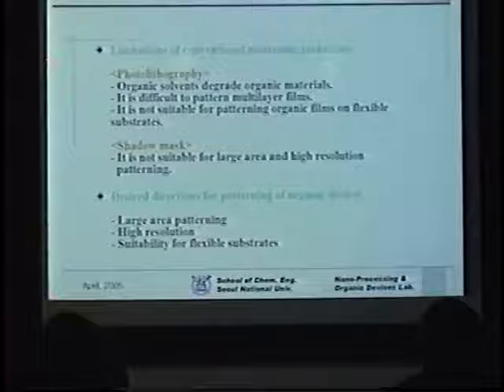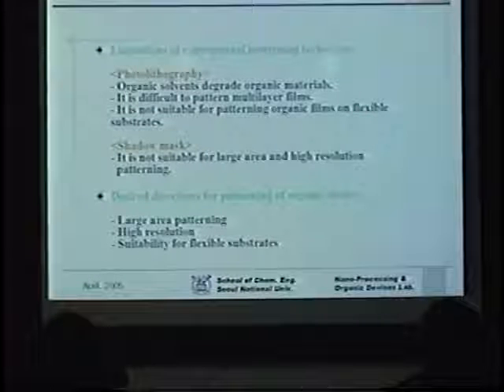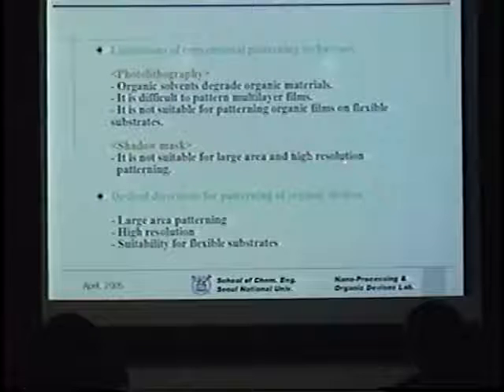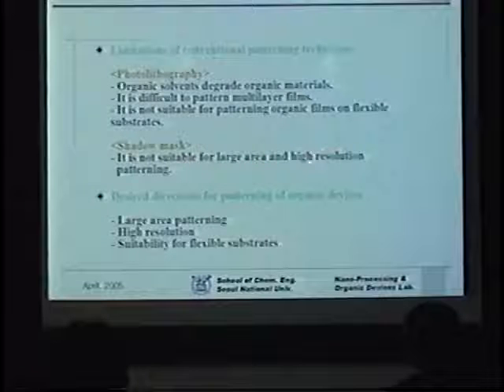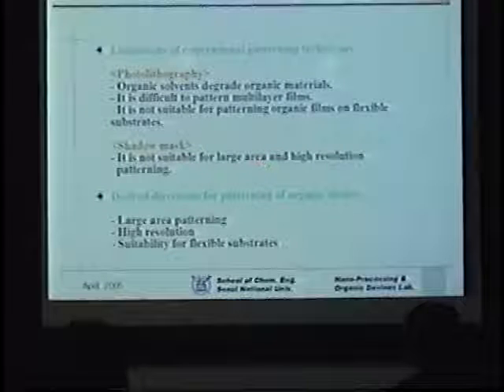And it's not suitable also for patterning organic films on flexible substrates because of the natural undulation inherently present in the substrate. And as indicated, shadow masking is not suitable for large areas, and neither is it suitable for high resolution patterning.